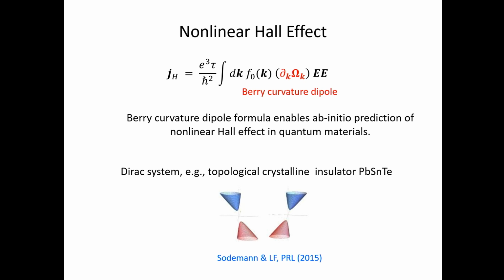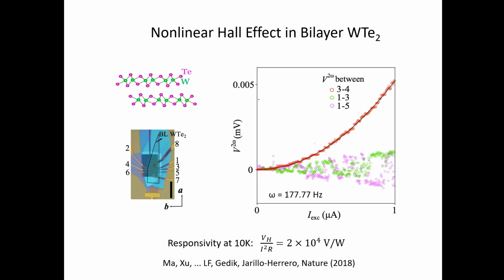Okay. In our early work, we considered a topological crystalline insulator. I won't go into the details. These are materials which have a surface state which, under structural distortion, generates a Dirac mass. So we have a massive Dirac fermion that carries Berry curvature. Also, in these cases, the Dirac cone is tilted, so there's a preferred directionality. There's a Berry curvature dipole in these lead selenide, lead telluride materials. So that's our prediction from almost 10 years ago.